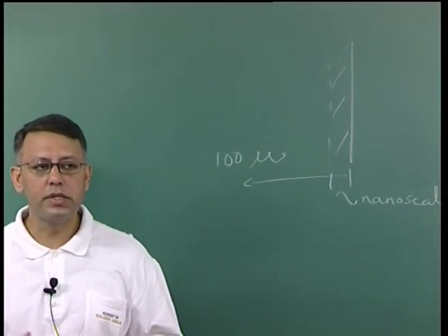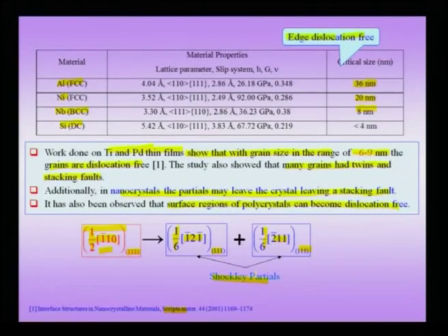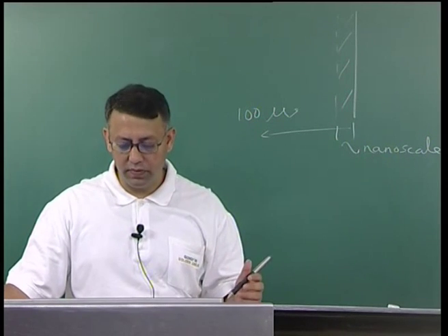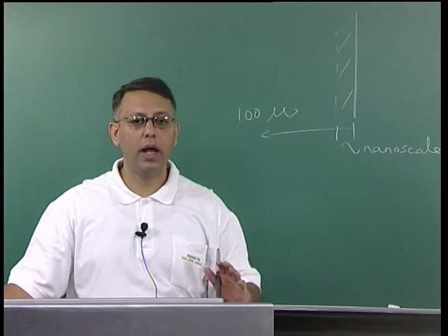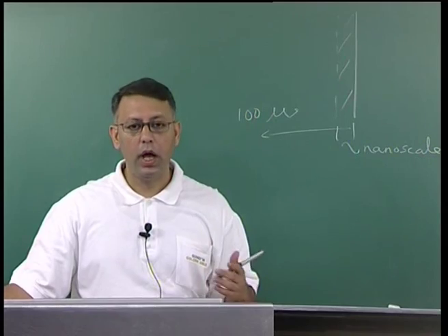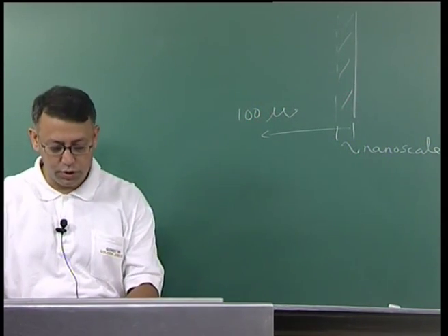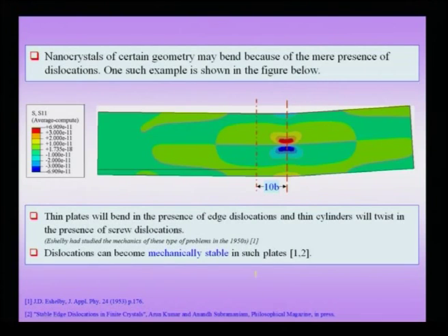So if you are working in a bulk crystal, there is some importance of image forces, but since this region is very small compared to the whole crystal, we tend to ignore it. But definitely in the case of nanocrystals, it is very clear that I cannot ignore image forces, and beautifully so, I now can recover my theoretical shear strength because dislocations may spontaneously leave the crystal, making it completely dislocation free and giving me the theoretical shear strength.